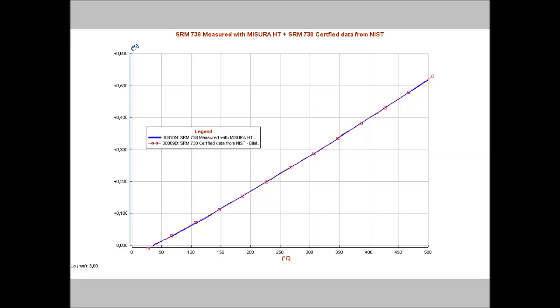The measurement is carried out with no contact on both sides of the sample, and for this reason it is an absolute measurement. In the traditional dilatometers, the sample is contained inside the measuring system, which itself expands with temperature. When the measuring system is made with alumina, the expansion of the measuring head may be much bigger than the expansion of the specimen itself. For this reason, it is absolutely necessary to apply a correction curve, which accounts for the expansion of the measuring system. In the optical dilatometer, the sample is completely free, and it is not necessary to record and use the procedure of the calibration curve.